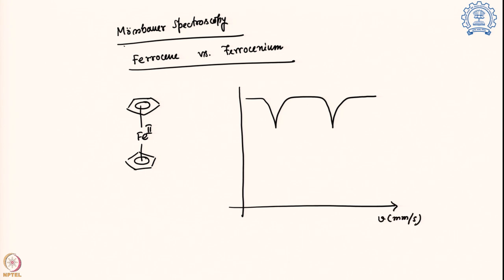Anytime you are drawing it, we should define the axes: one is the transmittance and one is the velocity. Over here the peaks are very well separated. The delta EQ value is close to 2.39 millimeter per second. And if we take these two values and take an average of that, which will be the delta value, it comes around 0.53 millimeter per second.